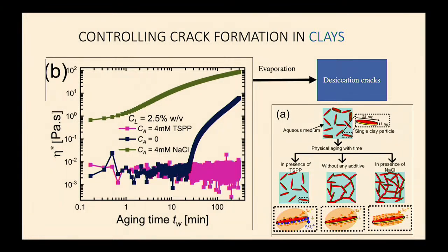When you added the salt, immediately these Debye layers started collapsing, the particles came together, formed these aggregates, formed the gel, and we started measuring this, as you can see from 0.2 minutes, it's a solid. So now let's see how these crack, because we know that it's really the elastic samples that are going to crack within a reasonable time scale. All the experiments that I'll show you after this are done with the sample with different amounts of salt.